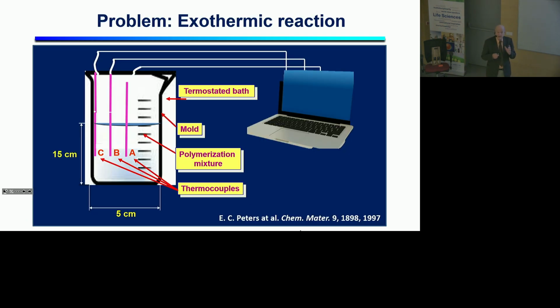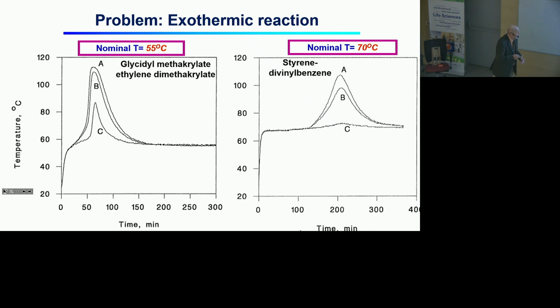Problem is, if you want to make large monolith, because the polymerization reaction is exothermic, and therefore we have to deal with the heat of polymerization. So Eric Peters essentially prepared this experiment with 3 different thermocouples measuring temperature at 3 different locations. And if you look at what's happening during this large-scale preparation of the monolith, you see that with the methacrylates, after about less than 1 hour, we see the increase in temperature in the middle from the nominal 55 degrees C to about 110 degrees C, which is a big difference.